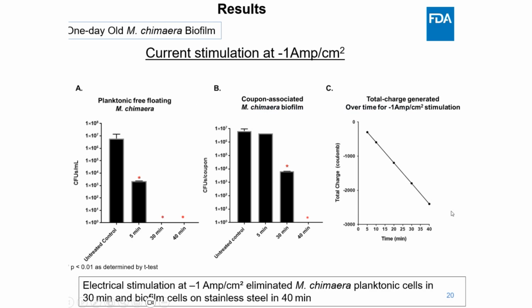Since cathodic voltage alone was not sufficient to fully eradicate early NTM biofilms, we next tested whether applying cathodic current could enhance efficacy, targeting both biofilm-associated and free-floating, or planktonic, Mycobacterium chimaera cells. Here we applied a current density of minus 1 amp for various durations: 5 minutes, 30 minutes, and 40 minutes. We then did the same study as previously and looked at biofilm viability compared to the untreated control.